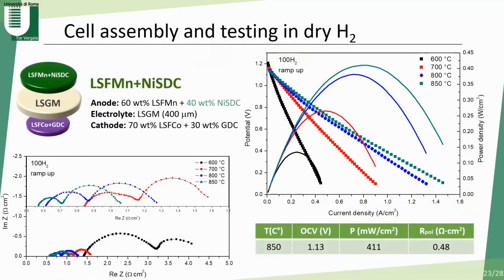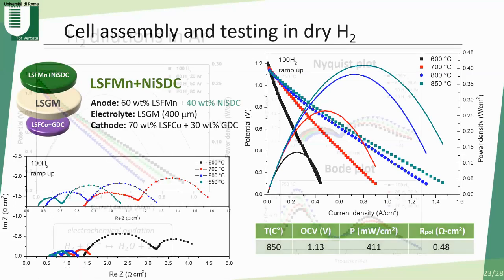We used our composite anode in single cells, which are electrolyte supported, using lanthanum, strontium, gallium, magnesium as electrolyte, a well-known electrolyte for intermediate temperature application. And we made a pellet of 400 microns. Then we tested in this temperature range, firstly by using hydrogen. And we got remarkable results, more than 400 milliwatt per square centimeter, with a polarization resistance less than 0.5, which is good for this system.